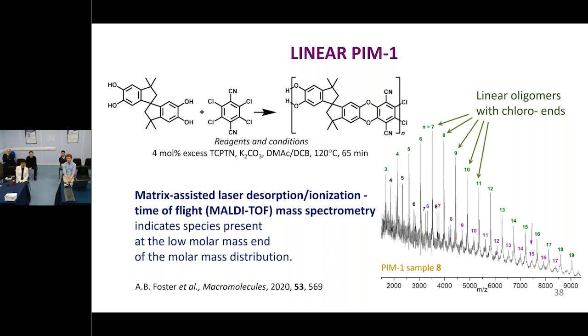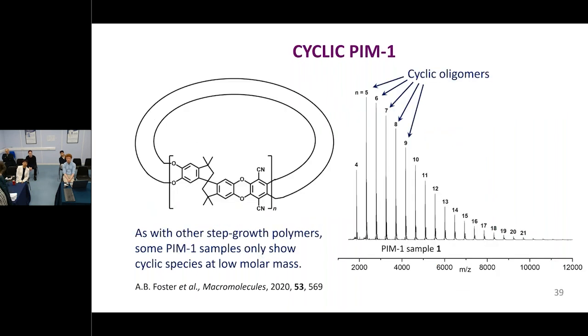In this particular sample, we can tell that at least at the low molecular weight end of the distribution, we've got some actual linear oligomers. Actually, in this case, we're using the chloromonomer, and with the chloro ends, we very rarely see the hydroxyl ends. They don't want to hang around. More commonly, with any step polymerization, what you actually see in that molecular range is cyclics.